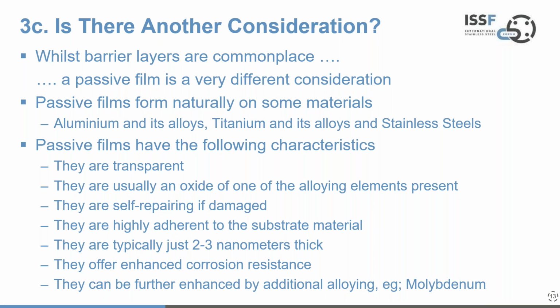Is there another consideration though? Barrier layers are very commonplace today, but a passive film is a very different consideration. And passive films form naturally on some materials, and we touched on those earlier, aluminium and its alloys, titanium and its alloys, and stainless steels. And really, it's fair to say that passive films have the following characteristics. They're generally transparent. They are an oxide of one of the alloying elements present in the material or alloy.